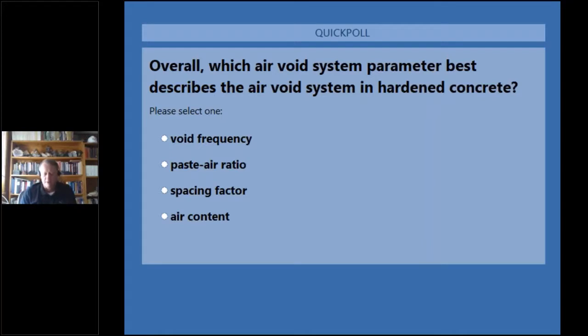Also, oftentimes when an aggregate particle plucks out of the cement, a little bit of the aggregate particle might still be stuck inside the void, and if that's the case, that's a slam dunk telling you that that's not an air void, but an aggregate piece that had been plucked out. So for those voids, closer scrutiny is definitely needed, but it's possible to do.